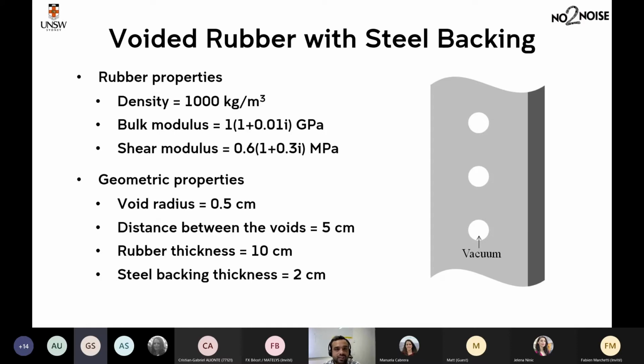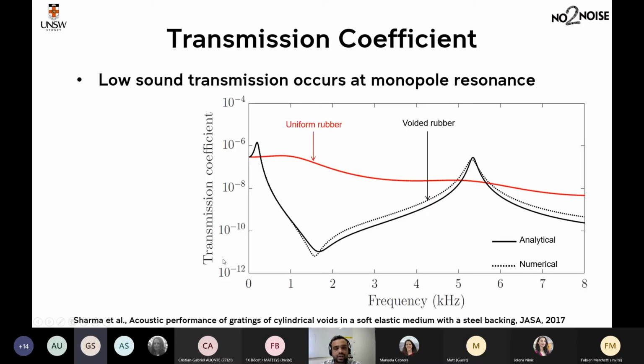Let's talk about what happens when you attach your coating to a steel backing. Just a reminder, when we have steel backing, we have water on the incident side and air on the transmission side. So there is a very heavy impedance mismatch here on the transmission side. These are the material properties. The material properties are similar. Geometric properties are slightly different here. Okay, so this is how the transmission coefficient looks. Because there's a very heavy impedance mismatch on the transmission side, the transmission coefficient is really, really small here compared to the water backing case, right?